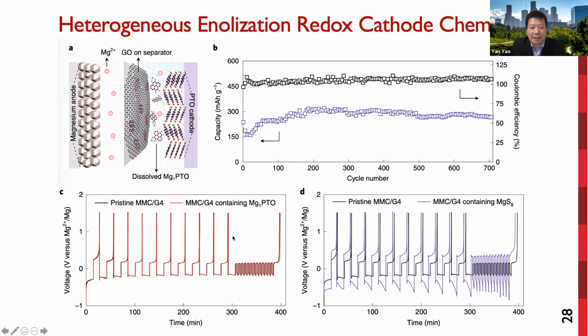On the second question about magnesium surface passivation, we test magnesium plating in G4 solution with and without magnesium 1 PTO. We see there's no variation in the overall potential in the plating and the stripping process, indicating there's also minimum change on the magnesium in the PTO cell. However, in comparison, with the magnesium sulfur reaction intermediate, we can see the overpotential has almost doubled. So this probably is related to the much higher solubility of the intermediate in the Mg sulfur process.